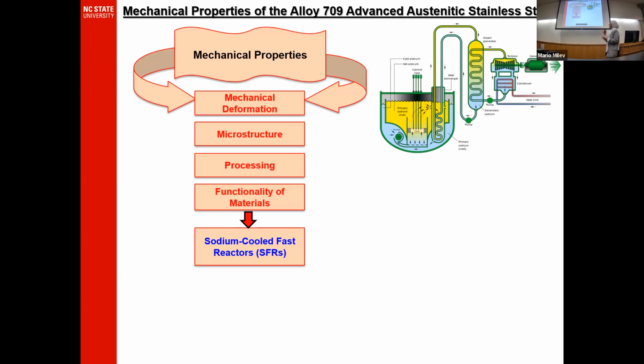The structural materials in sodium cooled fast reactor are subjected to cyclic loading during startups and shutdowns, known as fatigue damage, tension and compression. Also, the steady state operation introduces time-dependent effects like creep damage, which occurs at constant stress and temperature. The effect of creep and the effect of fatigue damage together can combine and cause a fast failure of the structural material of the reactor. This phenomenon is known as creep-fatigue interaction.